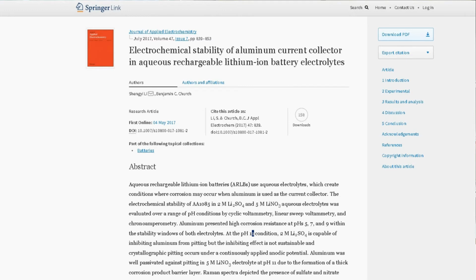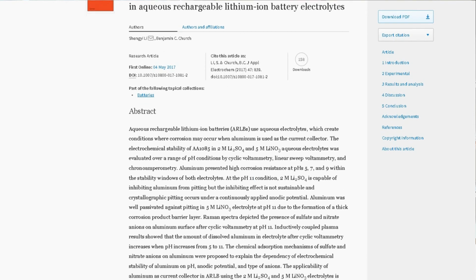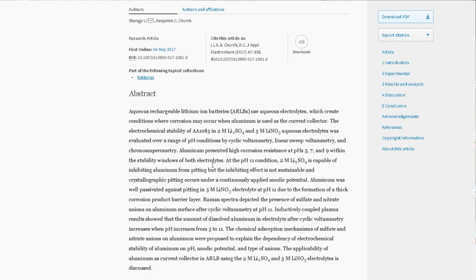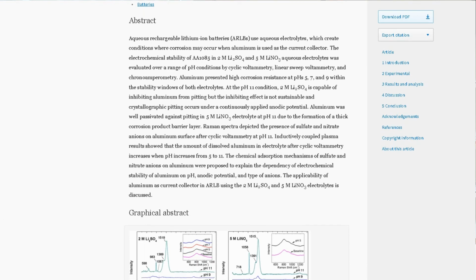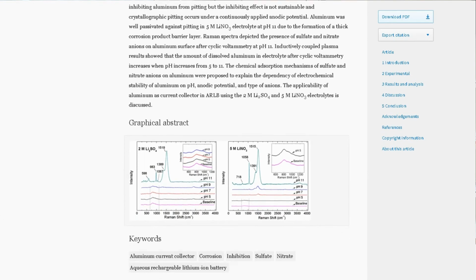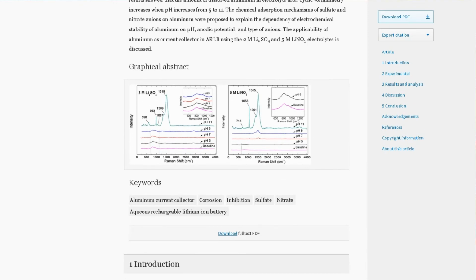If we got up to 2, 3, 4 volts, yeah, it would absolutely cause problems, particularly at alkaline pHs where OH- can start to attack the aluminum oxide. But for now, it seems to be okay. There are some additives we could put in if it starts to be a problem based on this paper, where it discusses using different additives like sulfate and nitrate to try to inhibit the degradation of aluminum oxide. So there are definitely options.